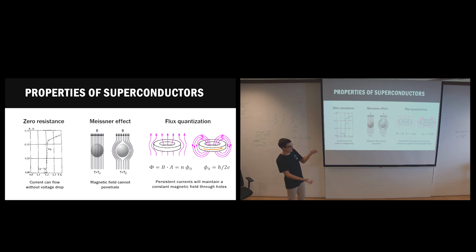So this allows us to see quantization with our bare eyes. And if we try to change it, for instance by putting a second magnet below the superconductor such that we increase the magnetic field lines, our superconductor itself will generate a current to oppose this change, because the field inside can only be 1, 2, 3 flux quanta, but it cannot be 1.1. So if I try to put 1.1, it will generate a current that fully compensates for this 0.1. So it's only 1.